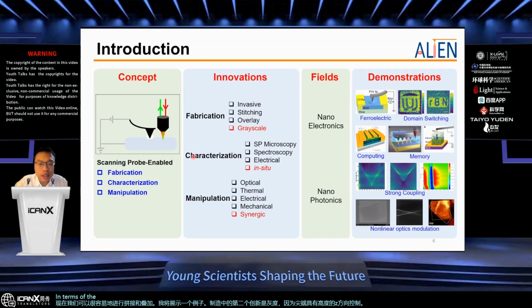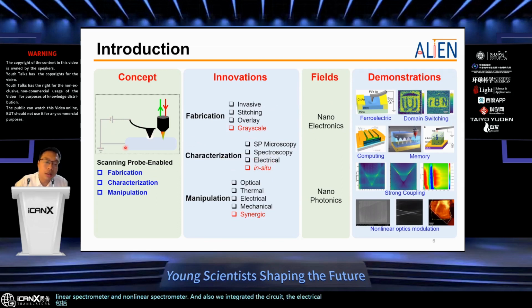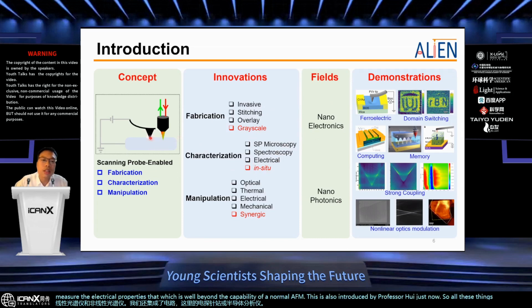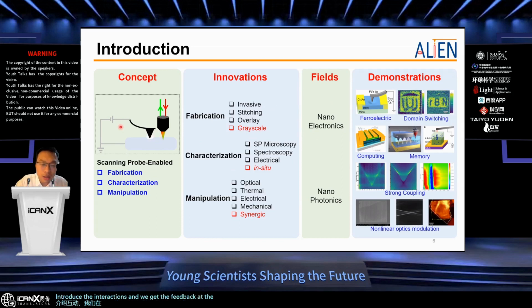The second innovation is the characterization, because the tip again is a scanning probe technology that allows us to do scanning probe based microscopy, for example, topography or C-AFM, just like Professor Hui introduced. And also by introducing the laser system, we are able to measure spectra, including linear and nonlinear spectroscopy. And we also integrated the electrical probe station, or the semiconductor analyzer, to measure the electrical properties, which is well beyond the capability of normal AFM. This was also introduced by Professor Hui just now. So all these things can be done at the same time, which means we introduce the interactions and we get the feedback at the same time in electrical, optical, and scanning probe-based microscopy.